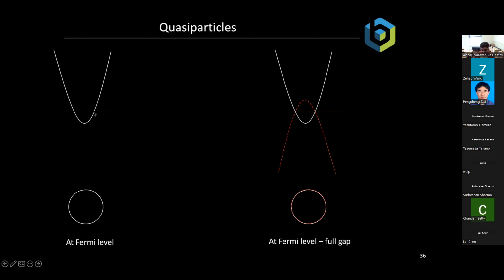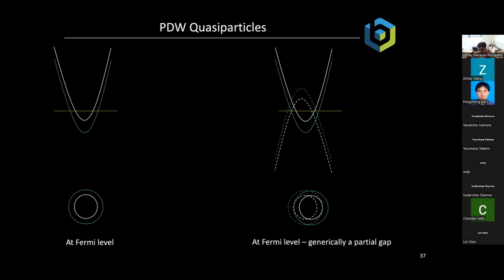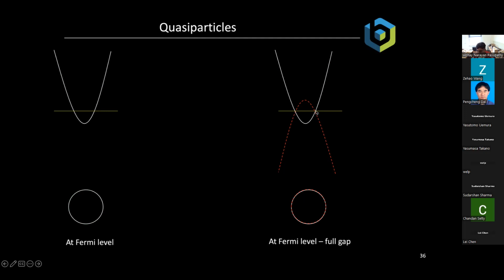When this material becomes a superconductor, then the prescription you have is the following. You take this white line, which is the normal state band structure, and you invert it. So you make it electron hole symmetric. That's this red dashed line. And you superpose these two on top of each other. That will give you a red Fermi surface and a white Fermi surface, both superposed on top of each other. And wherever these two intersect, a gap opens up. That gap is a superconducting gap. And so when I do this, I end up with a gap at the Fermi level.